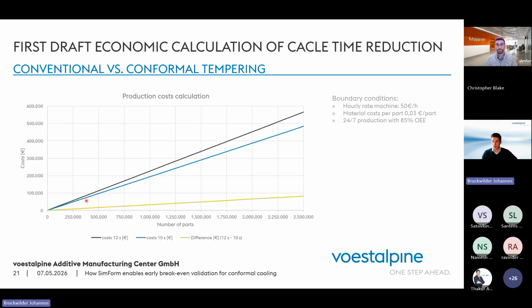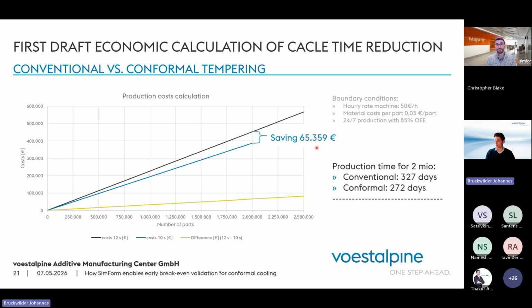And here you see the conventional cost, especially for 2 million parts, and also for the conformal cooling. And if you calculate it, the difference at 2 million shots could be a potential saving of 65,000 euro. And if you are looking for the production time that is needed, conventional, with these boundary conditions, you need 327 days, and with the conformal cooling, you need 272 days. So there's a difference of 55 days.